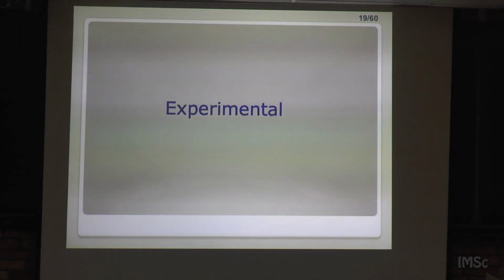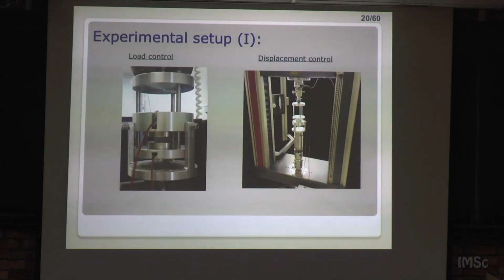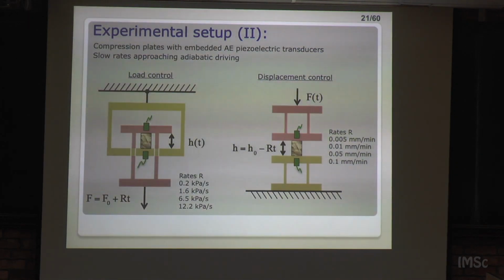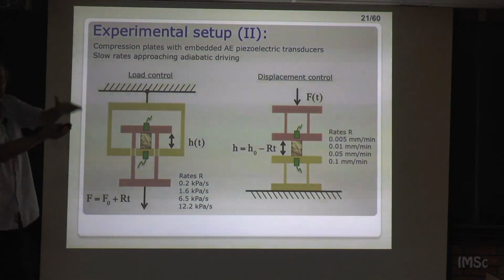Okay. So let's go to the experimental aspects of our measurements. These are the two kinds of setups that we use. We call them, one is what we call load control, and the other is displacement control. Let me just go to some schematics here. Essentially, we have a sample, which is a porous material, which is between two plates, two compression plates. In the plates, embedded in the plates, we have some acoustic emission sensors. These are like microphones, but they sense ultrasounds, not normal sound. Okay?